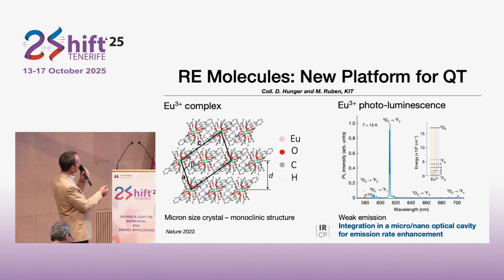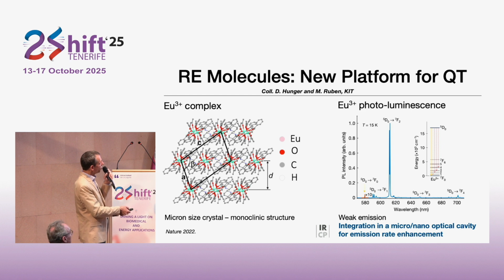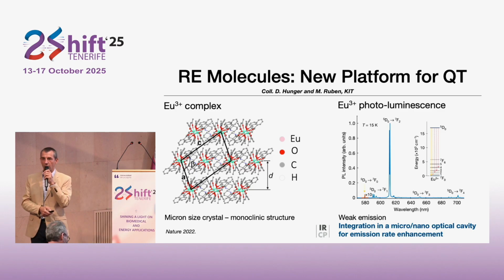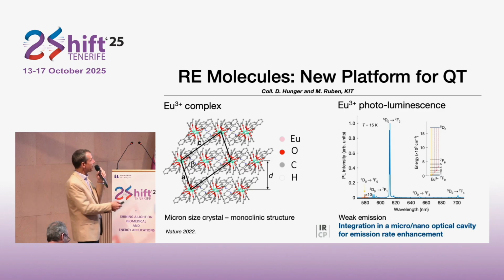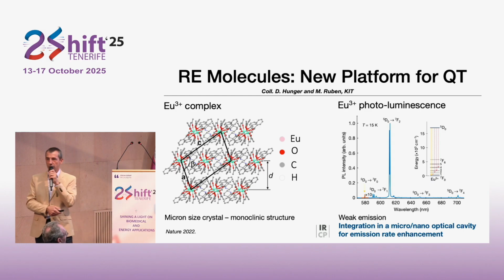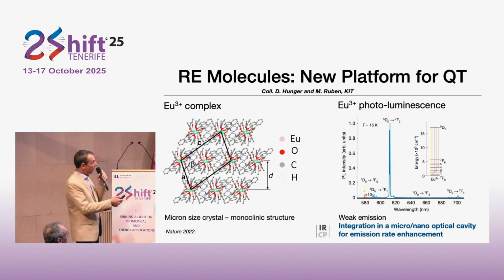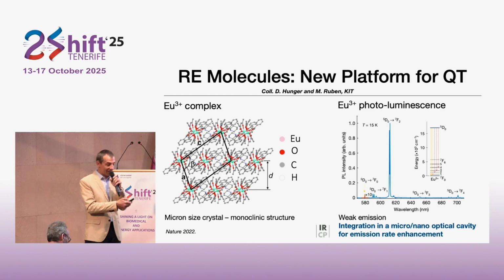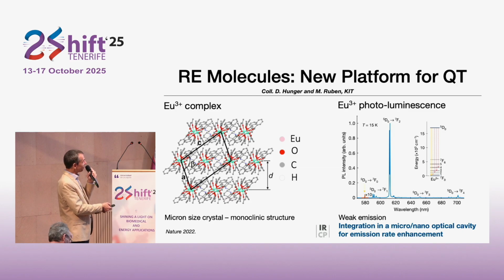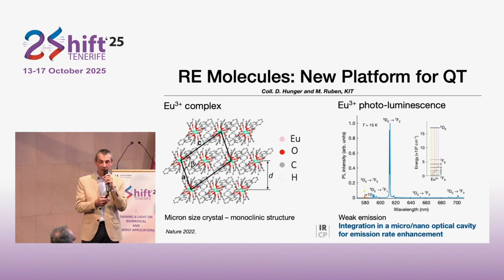Okay, so first we looked at europium photoluminescence. Here we changed dopant. We moved from ytterbium to europium. So europium photoluminescence at low temperature, nothing very special. The transition of europium of interest for looking at long-lived quantum states is the 5D0-7F0. In this particular compound, you see that it's very, very small. So this is really far from being ideal because, of course, with a weak transition, everything gets much more difficult. This weak emission, however, is the only one which can exhibit long-lived quantum states. All the other ones are too much perturbed by interactions with phonons. So we need to work with this one.